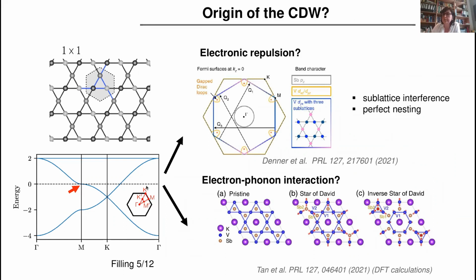So we can consider two scenarios. One is that this is a consequence of electronic repulsion. We know that exactly at the Van Hove singularity, we have perfect nesting. These are the three Q vectors in this kagome lattice, and this is perfect nesting. Therefore, one can expect that Coulomb repulsion, especially nearest-neighbor Coulomb repulsion, may be a strong enough interaction to just bring the system out of this instability.